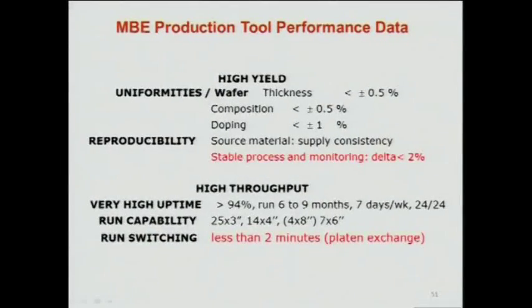And of course, we had to have performance, not just make it big. The uniformity of the MBE production system is very good, plus or minus 0.5% over the whole wafer. And most importantly, high throughput, 94% operating, running 6 to 9 months without opening the MBE system for refilling. It runs 7 days a week, 24 hours a day. And most importantly, the switching time from one platen to the next is all automated by computer control, with only 2 minutes for platen exchange.